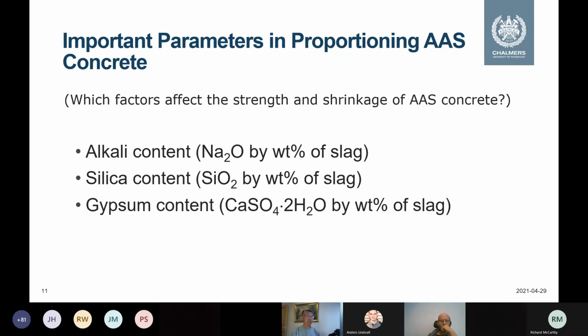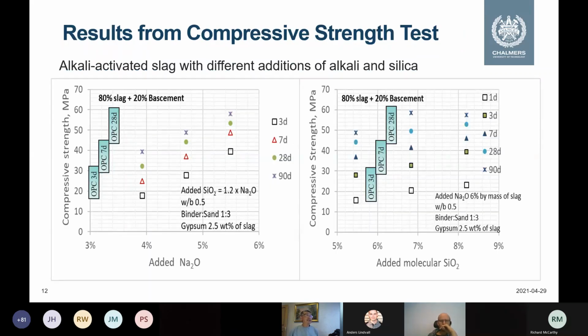So these 3 parameters we studied. You can see that by considering sodium oxide on the left side, if we consider 4% to 6%, between this 4 and 6%, we can produce concrete more or less like ordinary Portland cement. So here is ordinary Portland cement compressive strength. You can see 3 days, 7 days, and 28 days. It is in this range. So here, when we use, for instance, 5%, that exactly follows 3 days, 7 days, and 28 days.